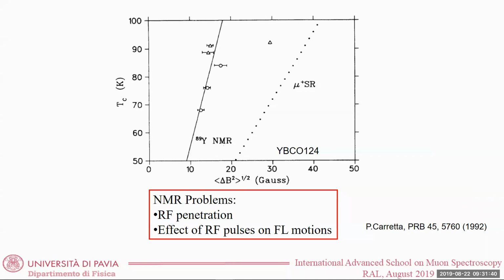So what I did in this study is to take, for example, this family of high TC superconductors and do yttrium NMR in the system and measure in the superconducting phase the modulation of the local field, which is proportional to sigma, the transverse field relaxation rate. And what I obtain with NMR are these points. There is one point here. But if you do μSR, you see something which is here.